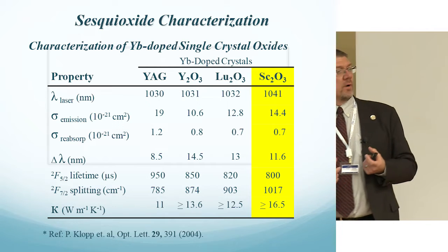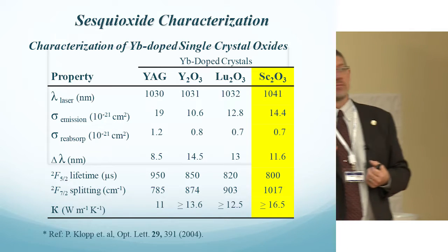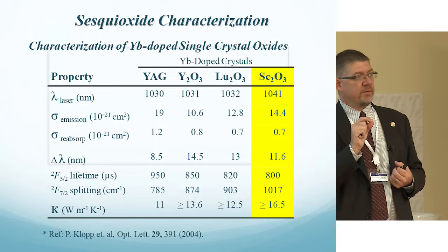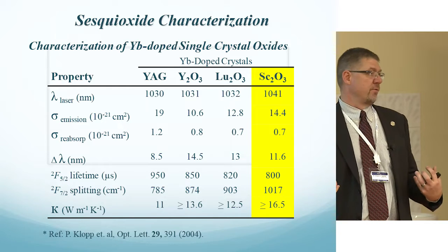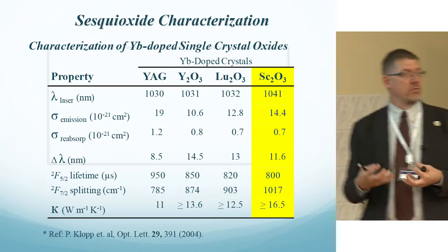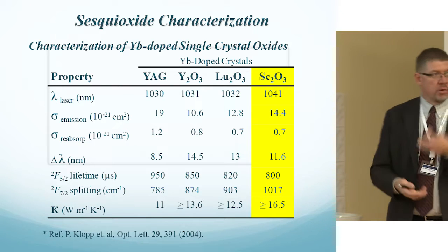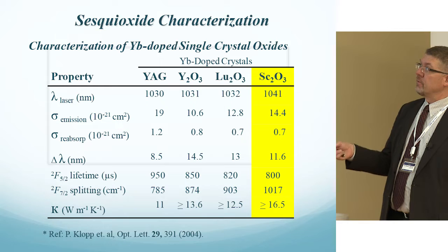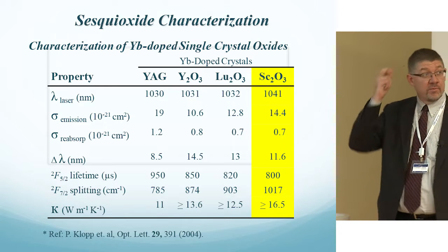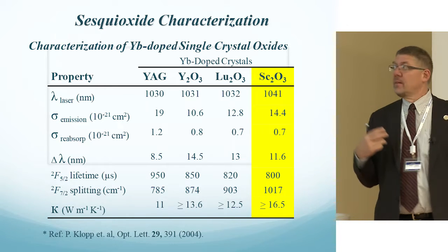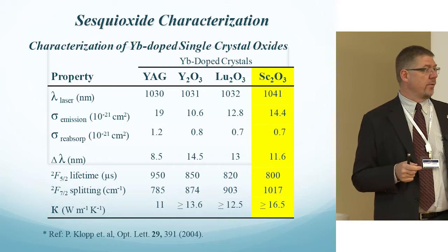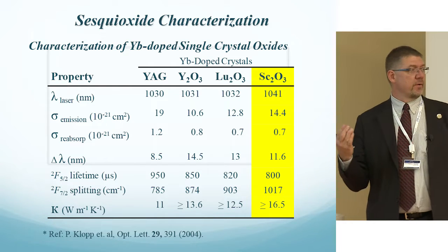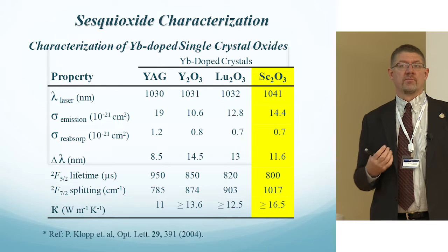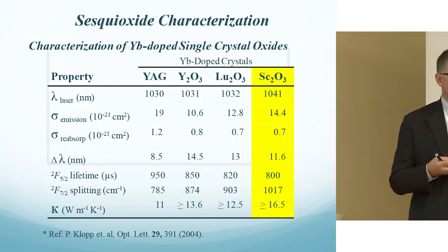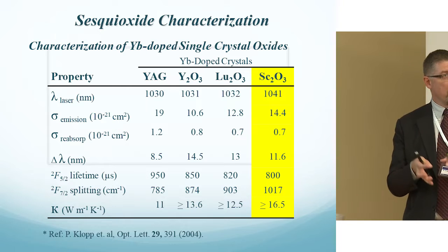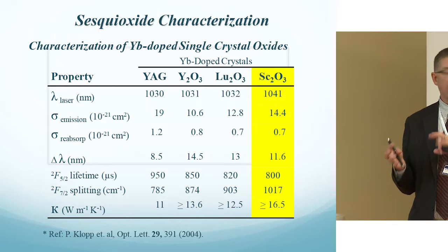So companies like Trumpf, who are manufacturing these thin disk lasers, want them to have their laser piece as thin as possible and bring the heat out through the faces and the edges. And you can't do that very well with a large piece of YAG, but you can do it pretty nicely with these. The sesquioxides were first grown back in the 60s at Bell Labs. Their melting temperature is about 2,300 degrees, 200 to 300 degrees higher than YAG. And most furnaces at that temperature are breaking down. It's hard to hold a material and keep it from going volatile on you at that kind of a growth